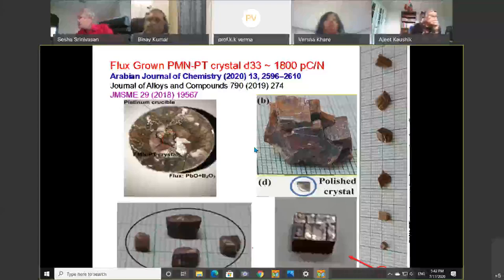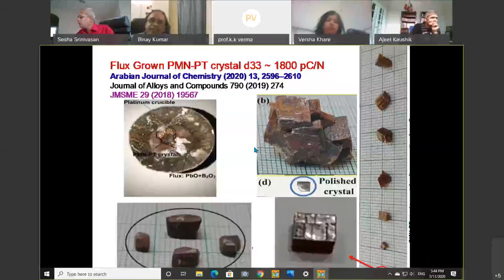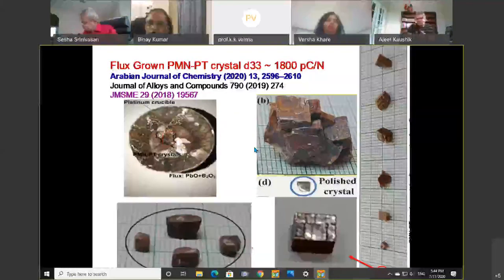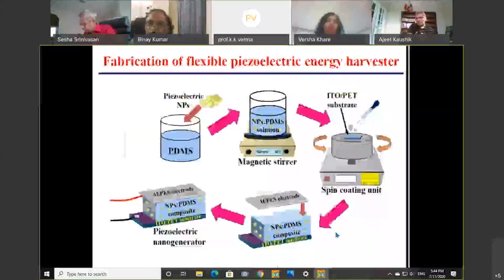Now, if we get nanoparticles of different materials, how do we go for the actual device? PDMS is an organic binder, you can say. It is also very slightly piezoelectric. We put the nanoparticles here, then use the magnetic stirrer, and then put it on an ITO or PET substrate, and then drop this material over it and get a structure something like this. From top and bottom, we have electrodes, and we have our material embedded inside, in between.